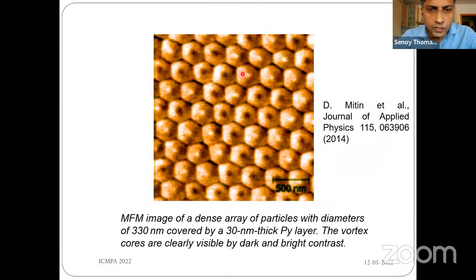Okay, we also routinely do magnetic force microscopy to have more information on the spin configuration in such magnetic nanocap structures. Here is an MFM image recorded on 330 nanometer SiO2 spheres, which were deposited with 30 nanometer thick permalloy thin films. One could see that at the center of these spheres, or at the center of the cap, there is a contrast. The MFM is sensitive to the stray field directed perpendicular to the plane of the sample, so this contrast arises from the core magnetization. One could see the bright contrast as well as the dark contrast, which means that the core magnetization is pointing up or pointing down.